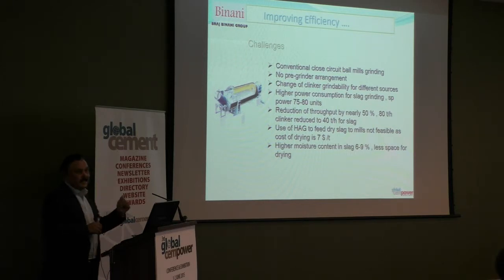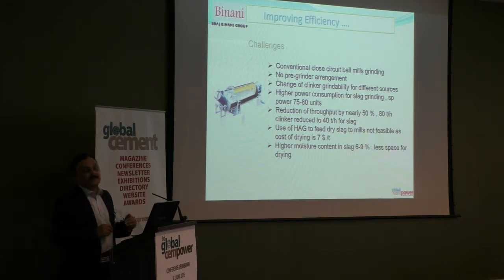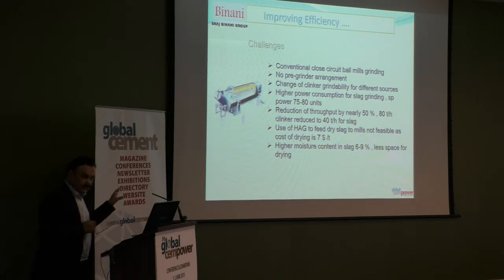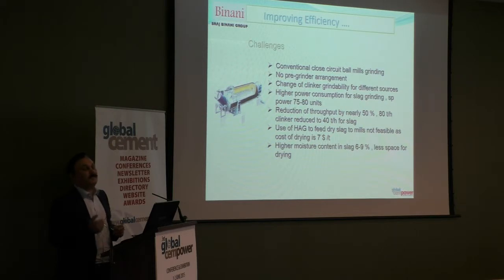Again, if you are grinding slag, then it will come to just half. From 80 tons, it may come down to 40 tons per hour. Higher moisture, you have more problems. So these are system design limitations. Well, you can't use HAG to dry slag because worldwide slag is never available as a sun-dry material. You have moisture which may range from 5% to 10%. You have to use some kind of drying mechanism. In our case, in both the mills, a hot gas generator is installed, but currently we are not in a position to use it because of the cost involved.